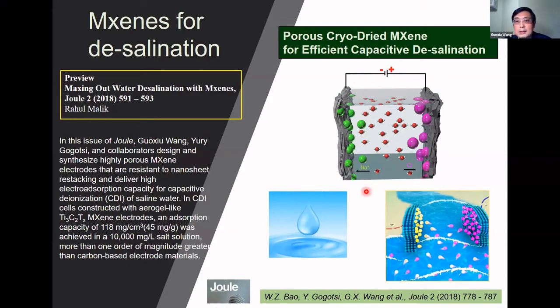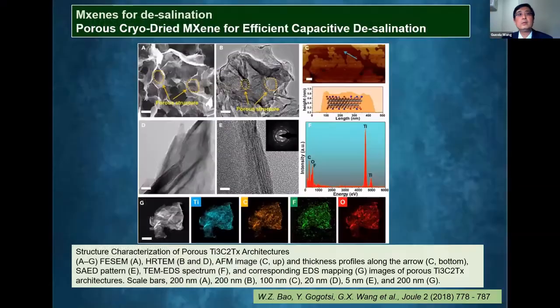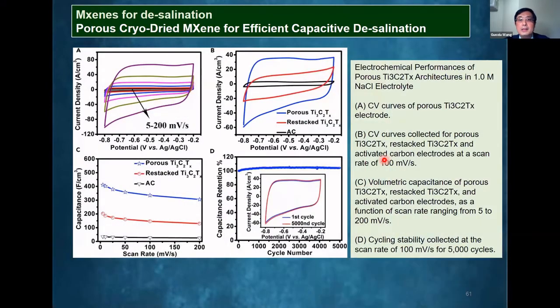So we constructed this kind of electrochemical cell for testing the capacitive desalination of MXene electrode materials. So here we use a freeze-dry method. We can obtain porous MXene materials. This method can efficiently prevent the restacking of individual MXene nanosheets. So this is the capacitance. You can see the porous MXene shows very high supercapacitance.